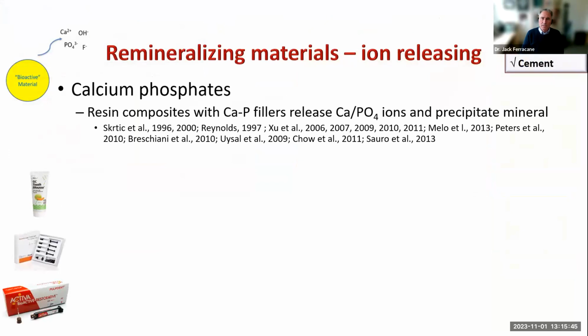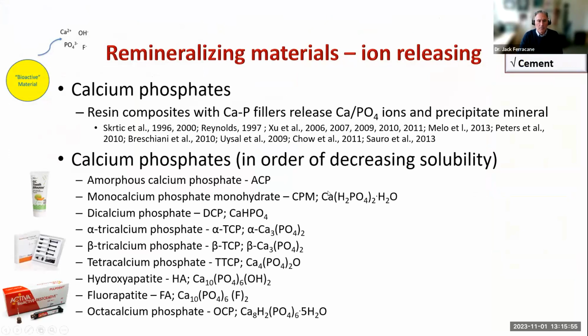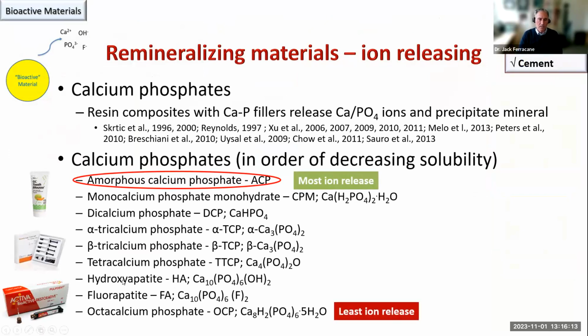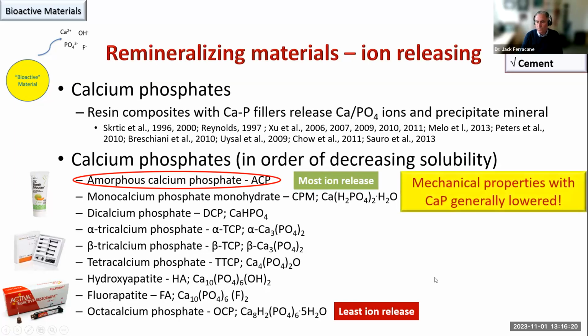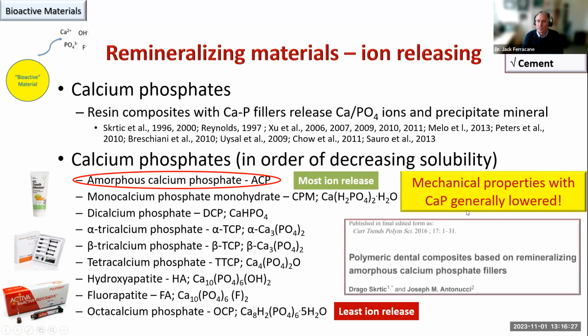Other mineralizing materials rely specifically on calcium phosphate. Calcium phosphate's been used in a variety of ways. Typically, it produces negative effects on the mechanical properties, though, and this has been an issue. But if you see this, we see amorphous calcium phosphate and monocalcium phosphate monohydrate being actively used because they are highly ion releasing. As we go down the scale here, we go from highly ion releasing to very low ion releasing, as we expect as we get to hydroxyapatite, fluoroapatite, and octacalcium phosphate. Very difficult to get the calcium out. So we mostly see materials at the top of the scale being used as additives. Again, as I mentioned, mechanical properties tend to generally be lowered. A very nice paper back in 2016 by Drago Skrtic and Joe Antonucci on this.